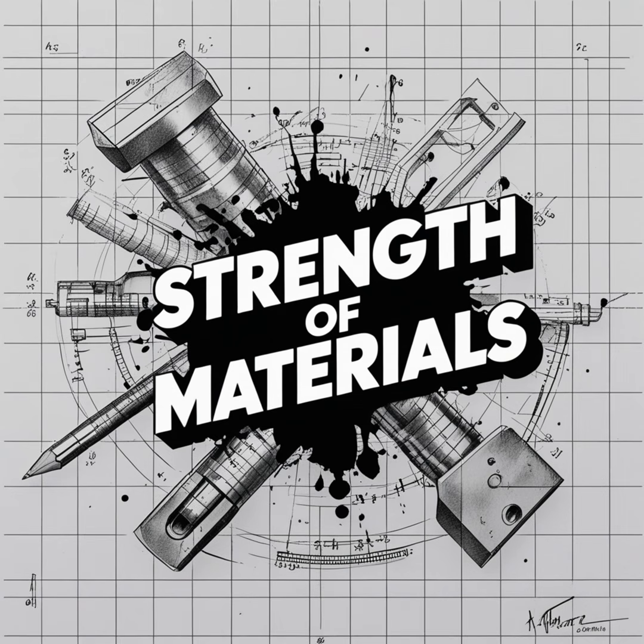Let's walk through them. Let's start with Soderberg. The Soderberg model was developed for the paranoid engineer. It is incredibly conservative. Paranoid engineer, I like that. It essentially says that as your static mean stress climbs closer to the material's yield point, the point where it starts to permanently bend, your allowable safe cyclic vibration drops in a straight line down to 0. So it's super strict. Very. If you are resting at the yield point, you cannot tolerate any vibration at all.